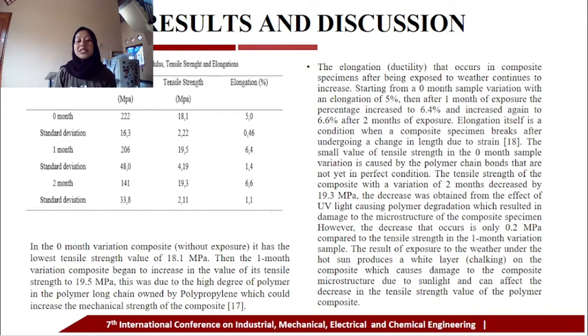The small value of tensile strength in the without exposure sample is caused by the polymer chain bonds that are not yet in perfect condition. The tensile strength of the composite with a variation of 2 months decreased to 19.3 MPa. The decrease was caused by UV light causing polymer degradation, which results in damage to the microstructure of the composite specimen. However, the decrease is only 0.2 MPa compared to the tensile strength in the 1-month variation sample.